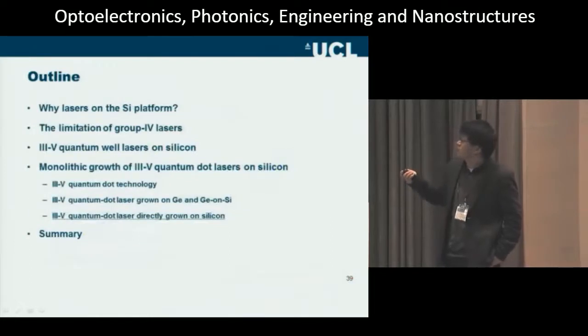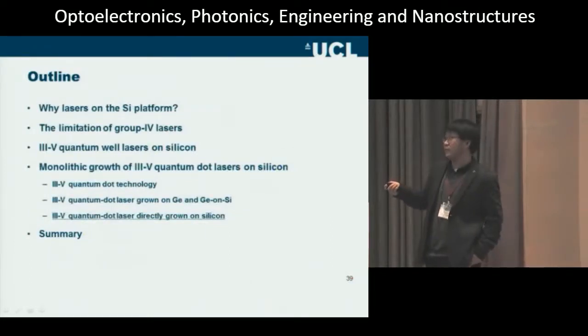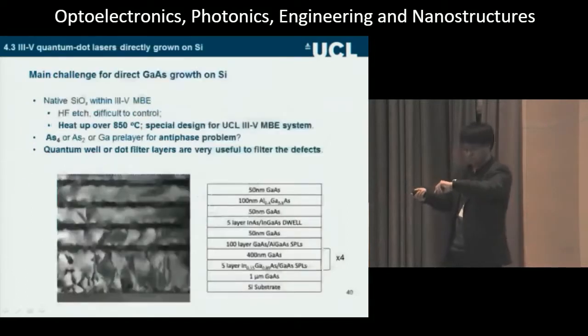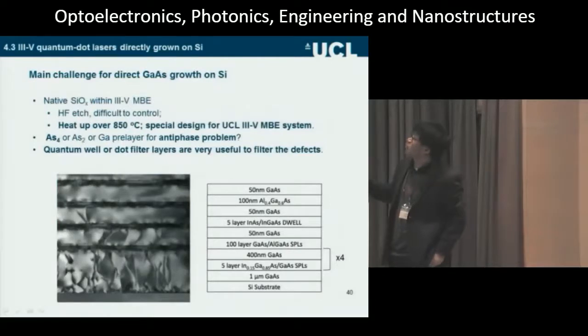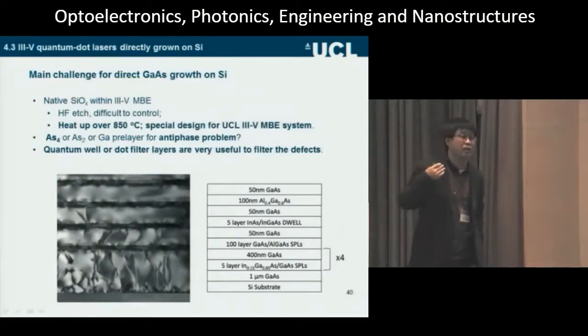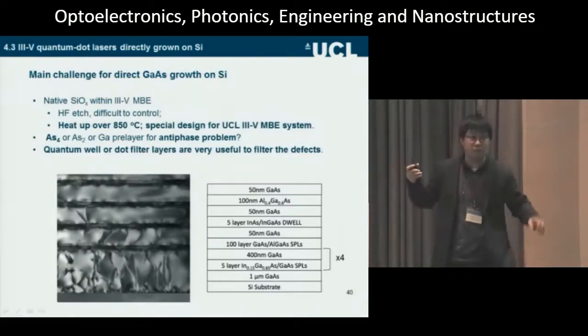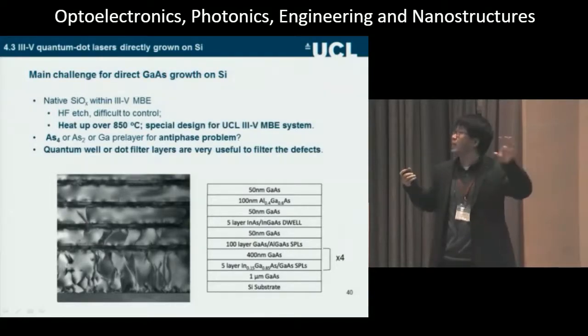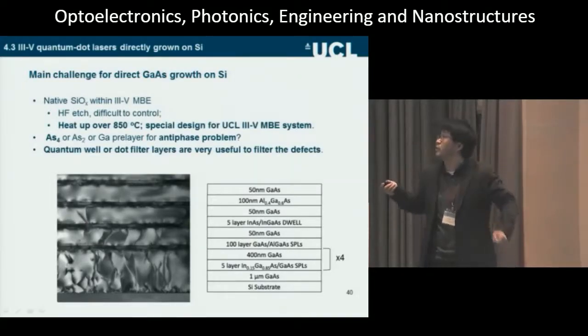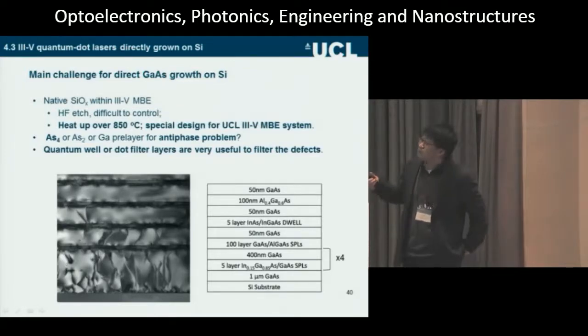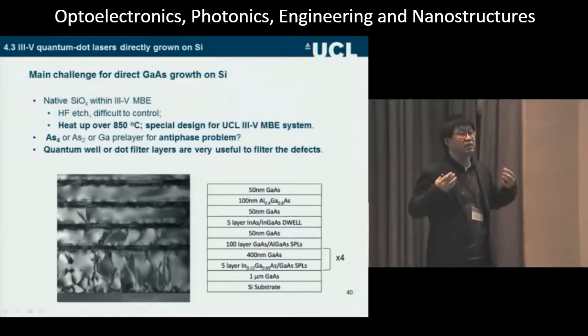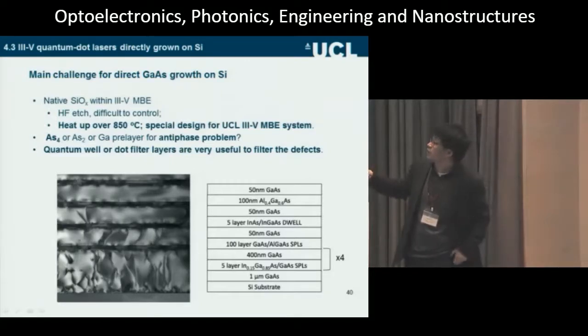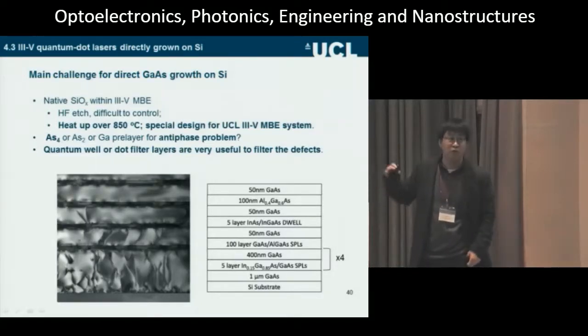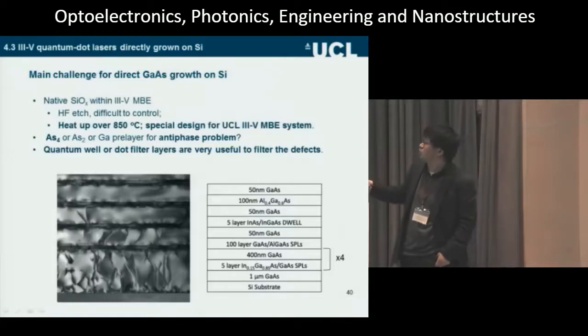So that's one approach. Actually, we did get funding after that to grow quantum dot lasers directly on silicon. Growth on silicon is a long-standing issue because you have two problems. One problem is anti-phase domains, and the other is threading dislocations. In my opinion, the most difficult one is how to clean the silicon oxide. We use direct heating up to 850 degrees, we use arsenic to suppress the APDs, and we use dislocation filter layers to filter the dislocations.